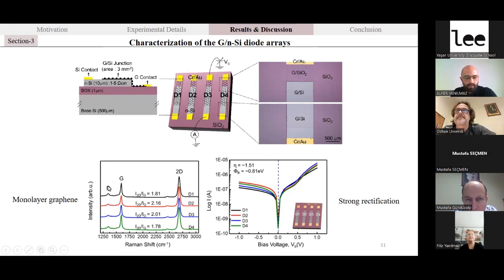Here we can see the defect peak is very low, and the intensity ratio of the 2D and G peaks shows that monolayer graphene was transferred successfully onto the device structure. And then we did the electronic measurements, the IV measurements of the devices under dark environment. We get the ideality factors and the Schottky barrier height of these individual devices, nearly the same and in good agreement with each other. And also strong rectification is observed after these experiments.